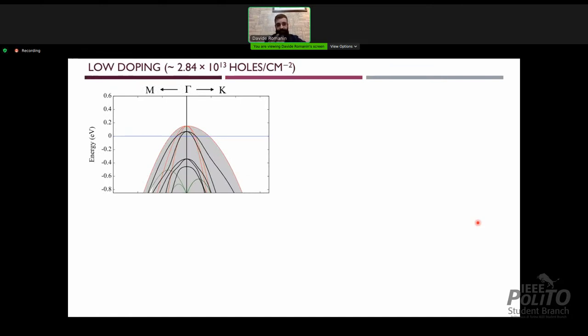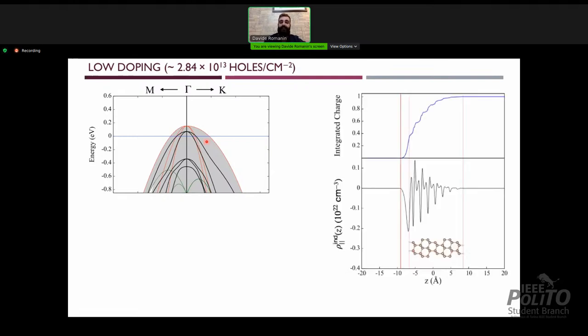Here I'm showing you the electronic band structure in reciprocal space. The black line is the dispersion of the surface, while the gray shaded region is the bulk projected over the surface. Therefore, we can say that we have electronic states at the Fermi level, here the blue line, if the black line falls inside the gray shaded region. Otherwise, it is called a surface-like state. Now, we can clearly see that the black line falls inside the gray shaded region, therefore, at low doping, the system acts as bulk-like. And this is also confirmed by the induced charge density.